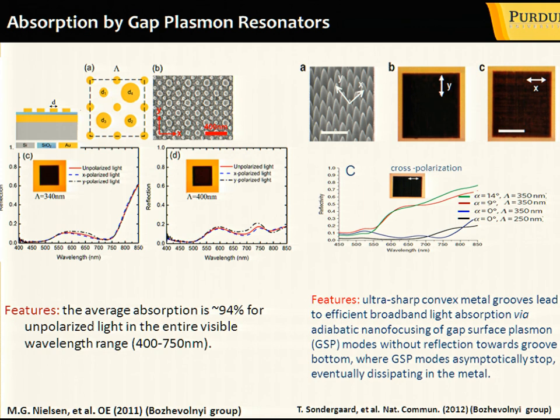Speaking of these perfect absorbers, as they call them, materials which absorb light in a very broad spectral range and for all angles of incidence, I was impressed with this work coming from the Bozhevolnyi group. He used simple metal discs of different sizes sitting atop a metal plate, and they support so-called gap surface plasmon resonance. And they resonate at different wavelengths so that all together they actually absorb light through all the visible part of the range and for all polarizations, unpolarized light. You see, and the absorption is actually 94%. It's a very efficient absorber.